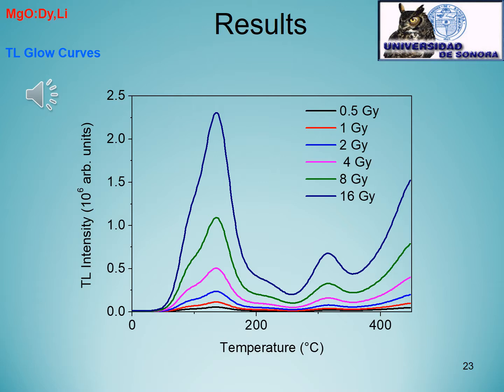We can observe at least two maxima located at very stable temperatures, and as we increase the dose, the intensity increases on the glow curve.